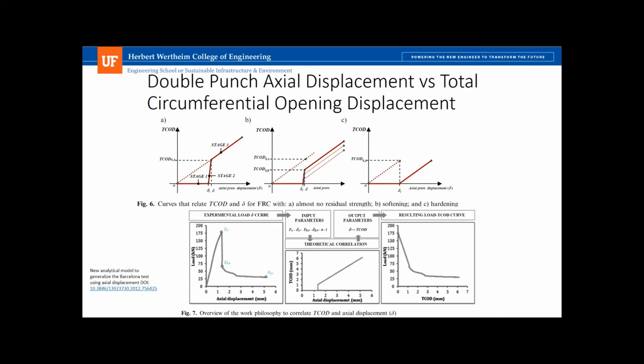So you get an axial displacement that does not relate to the circumferential displacement until the crack forms, and then you get a big jump in the circumference measurement, and you get a linear relationship between the circumference measurement and the axial measurement.